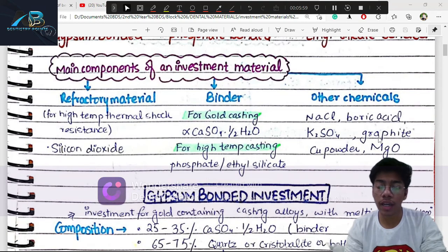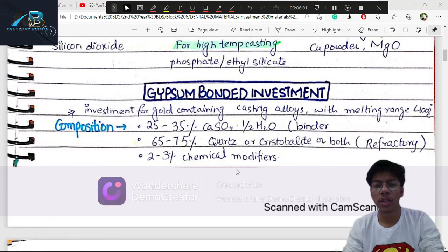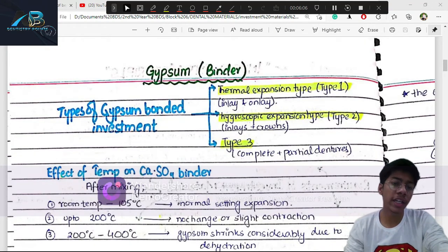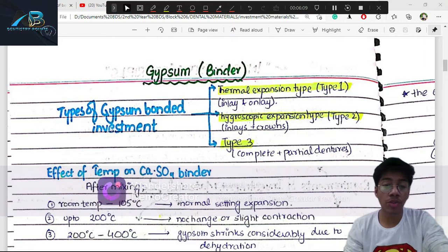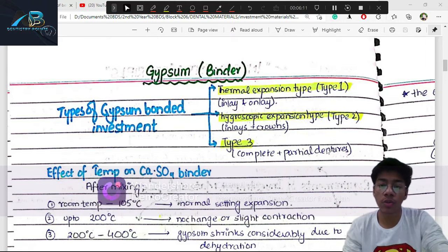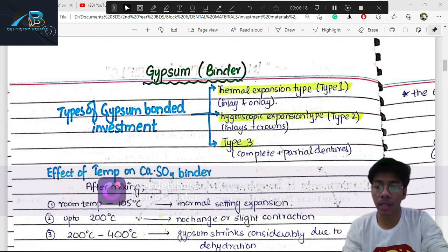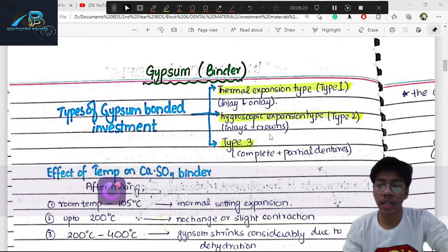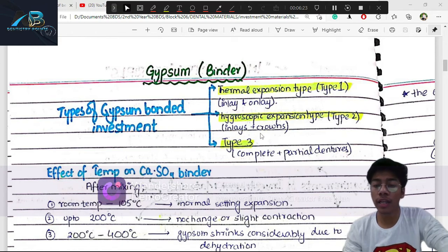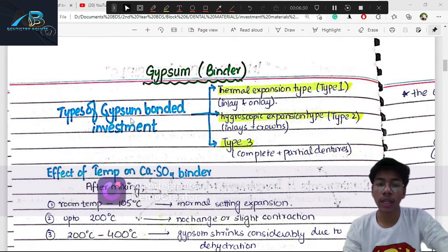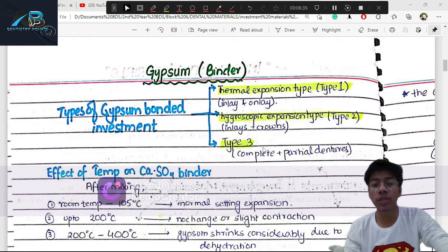There are also chemical modifiers — NaCl, boric acid — added at about 2–3% in small quantities to modify properties. Gypsum-bonded investment materials are classified into Type 1 (thermal expansion type, used for inlays and onlays), Type 2 (hygroscopic expansion type, used for inlays and crowns), and Type 3 (used for complete and partial dentures).